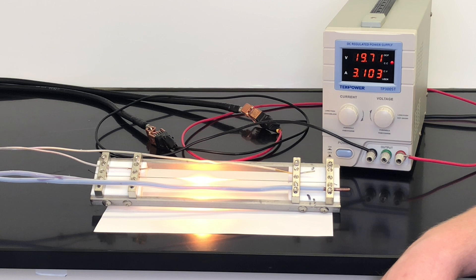The copper wire can actually sustain a higher temperature without beginning to degrade, so the reason that the CNT yarn performs relatively well compared to copper with the same linear mass is that the CNT yarn is much better at dissipating heat away from those hot spots.